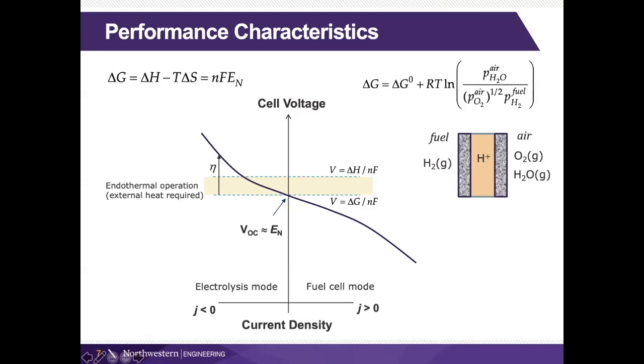And if we have a small overpotential such that we're below this voltage that corresponds to the enthalpy, we actually have to input energy into our system, a thermal energy into our system. On the other hand, if we operate at some higher voltage values, then we actually have heat release because our inefficiencies are so high, but that's actually not bad because we're using that heat to actually drive the delta H need for this system. Now, oftentimes we operate at what's called the thermal neutral point right here, such that our inefficiencies in catalysis exactly balance out the needs that we have for the heat input to actually run the reaction.